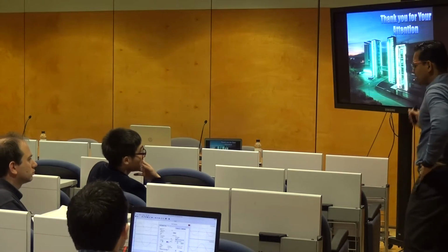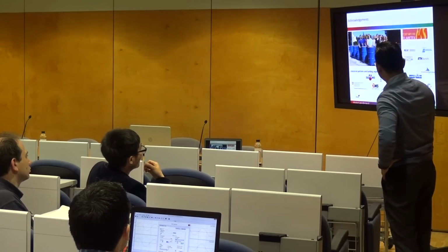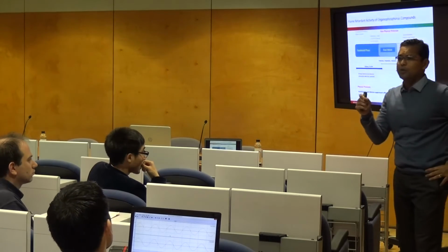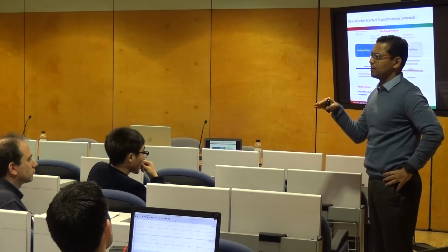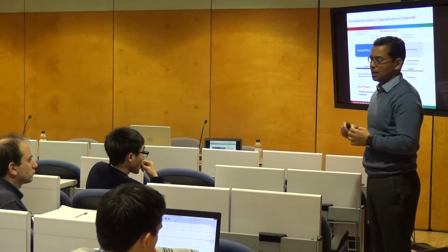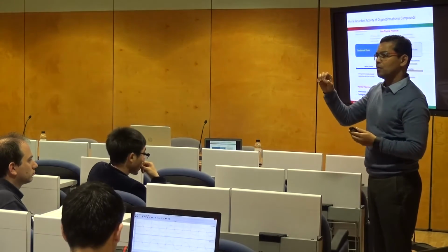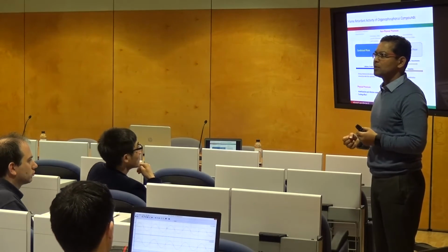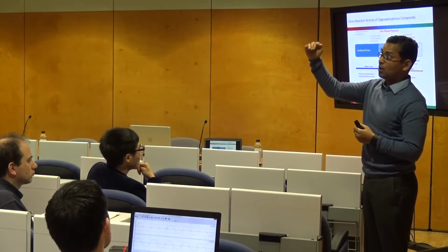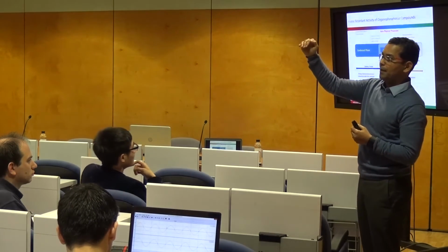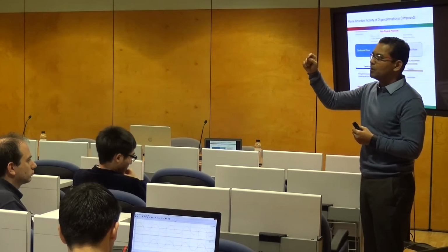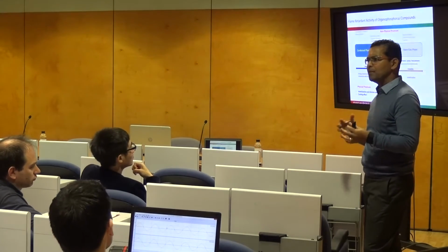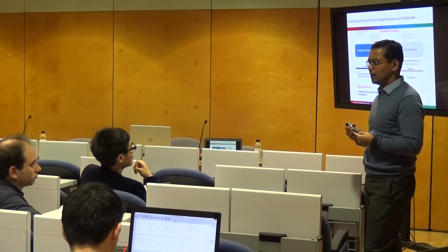Yeah, so something I did not talk about in this presentation is that we have seen, when we develop new additives for polyurethane, we're able to pass the UL94 test very easily. And we realized that the drips which are being formed are quite different when you add a flame retardant. Sometimes a lot of drips are formed, but some of these drips are not flammable drips. They are not flaming drips. So it's a very complex process. The whole flame inhibition process is quite complex.